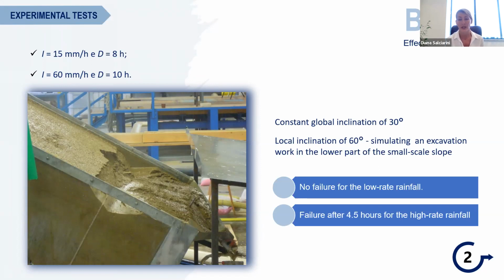We observed no failure for the low rate rainfall, and we observed failure, as shown in the picture, after 4.5 hours of rainfall for the high rate rainfall. Also, it is interesting to observe that prolonging this rainfall up to 10 hours, we observed no other failure in the artificial slope, nor erosion mechanism, except for the one located at the excavation work, despite the quite high global inclination.